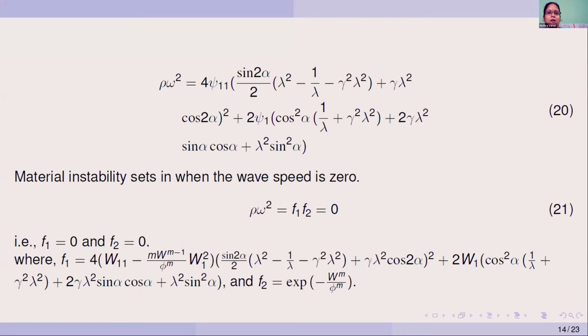So here we now plug in for the derivatives of the strain energy density incorporating failure in terms of the derivatives of the strain energy for the intact material behavior, W11 and W1, and we get the mixed conditions where material instability sets in, F1 equal to 0 and F2 equal to 0. Here F2 is the exponential function, and we can see that it does not depend on alpha, which is the orientation of the superimposed wave. And F1 depends on alpha. Here we consider F1 to be an implicit function of the shear strain gamma and orientation of the superimposed wave alpha for varying compressive stretch lambda.